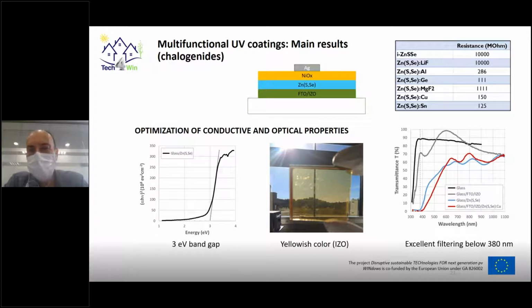These layers are synthesized by a sequential process where the metal zinc is deposited by sputtering, and then there is a reactive annealing in H2S and H2Se atmospheres. We observed a first problem: in these conditions, the selenium was able to react with the surface of the FTO and degraded the optical quality of the layer. So for this, we had to include an IZO, an indium zinc oxide layer, to protect the FTO.